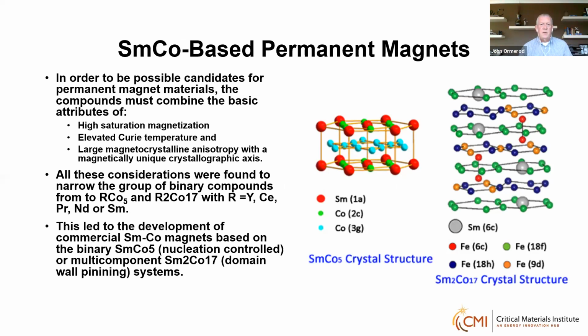Just to remind you, in order for a compound to be a potential candidate for a permanent magnet material, it really needs a combination of these basic attributes. It has to have high saturation magnetization. It has to have Curie temperatures significantly in excess of room temperature. And it has to have a large magnetocrystalline anisotropy, and importantly, that has to be coupled with a magnetically unique crystallographic axis. When these considerations were taken into account, it narrowed the candidate compounds to rare earth-cobalt-5 and rare earth-2-cobalt-17. This ultimately led to the development of the samarium-cobalt-based magnets, on either the binary samarium-cobalt-5 or the multi-component samarium-2-cobalt-17 precipitation hardened type materials.